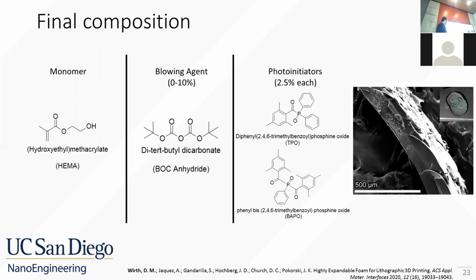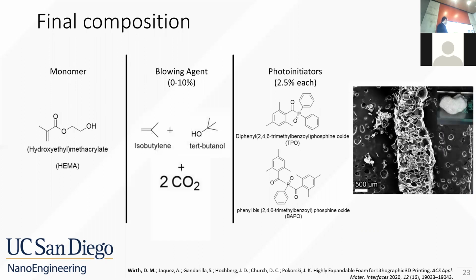But in fact, if it's heated above 150 Celsius, it decomposes into 4 moles of gaseous products, and it's fully soluble in the neat 2-hydroxyethyl methacrylate monomer. We also use 2.5% each of these industry standard near-ultraviolet photoinitiators.